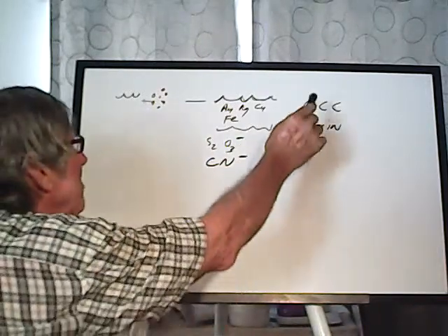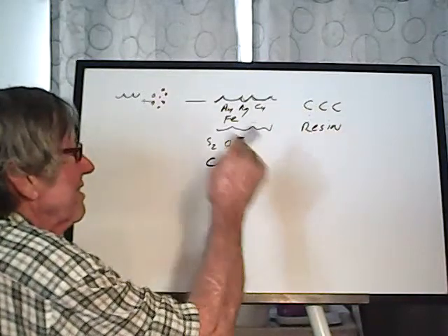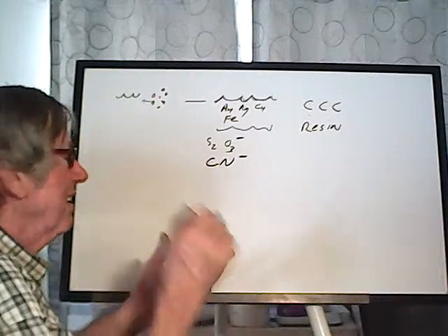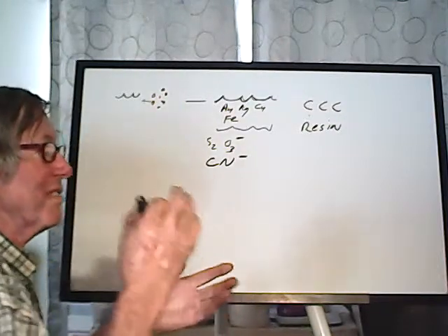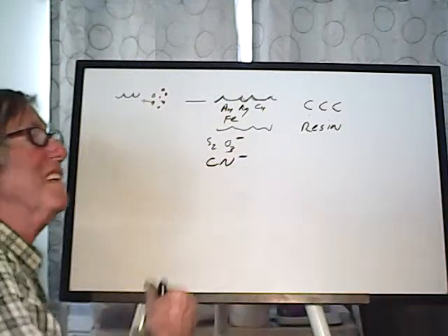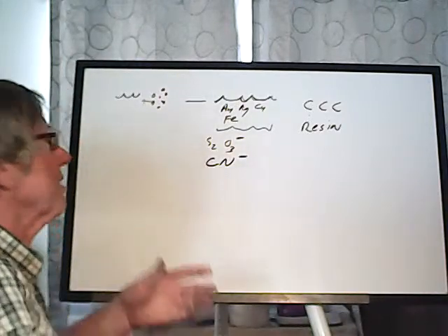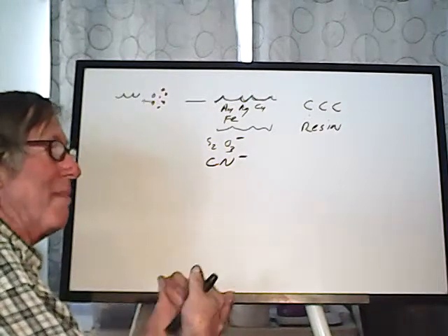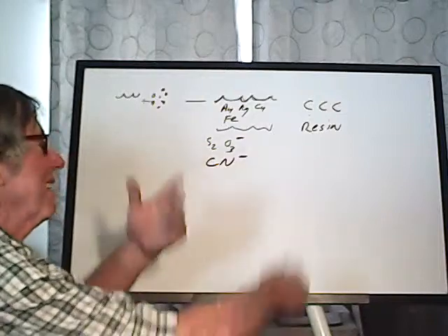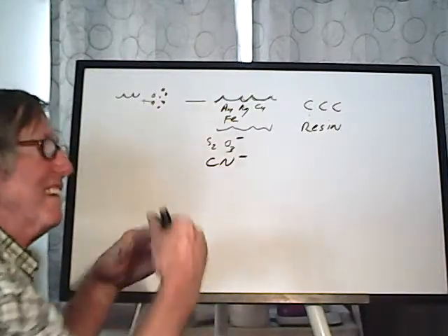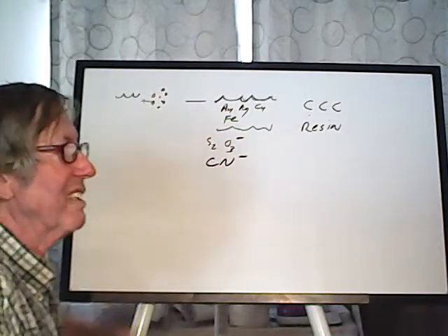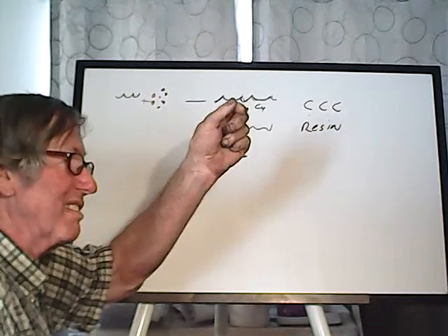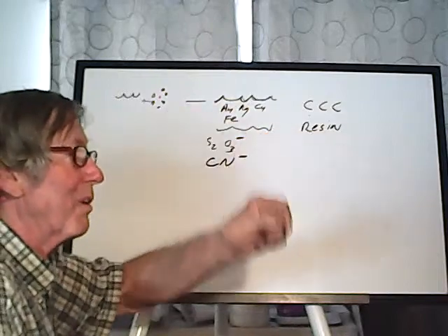But when you use zinc to precipitate the gold, then what happens is you first have to filter it real well. Then you have to deoxygenate it, because if there's oxygen in there, then the cyanide will tend to try and redissolve the gold. So by deoxygenating it, you stop that reaction. You throw in the zinc. It precipitates the gold. You filter it out again, and you can remove the solution. Then you take that sludge and smelt it. It's not as efficient because the particles in filtration are difficult. You can get very fine particles that go through your filters. And it's more expensive.